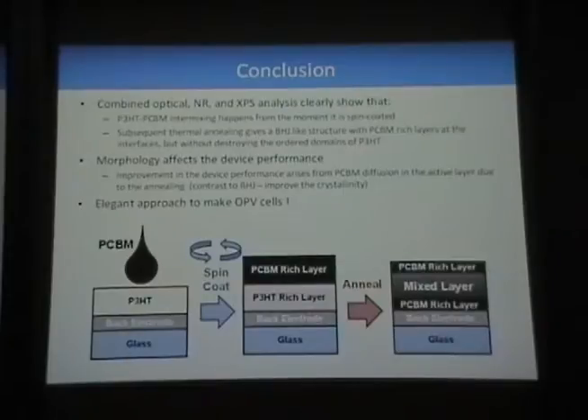We get a significant improvement in the device performance due to the PCBM diffusion into the active layer due to the annealing. So this is slightly different to the reason why you do the annealing in the BHJ, that is to improve the crystallinity. As I demonstrated before, you already have good crystallinity in your as-cast structure of the P3HT.